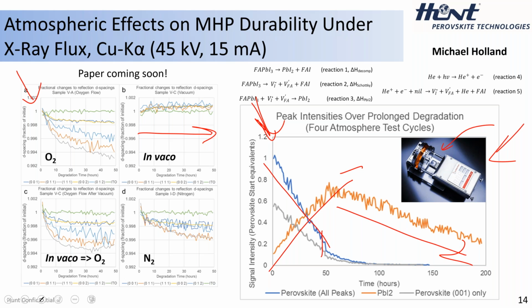And you can see now we expose the system to oxygen right after being under vacuum, and you get the same change in the unit cell volume as you do if you just do oxygen by itself. So it's not solvent degassing or any of that kind of stuff, things that would be irreversible. There's something different going on under vacuum. The material is changing in a different but yet positive way under vacuum versus the negative way it changes under oxygen. Same thing under nitrogen. We also have this reduction in the d-spacing over time with exposure, but not as intense as with oxygen.